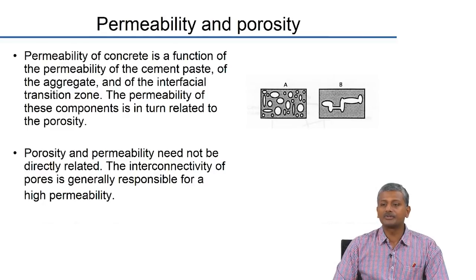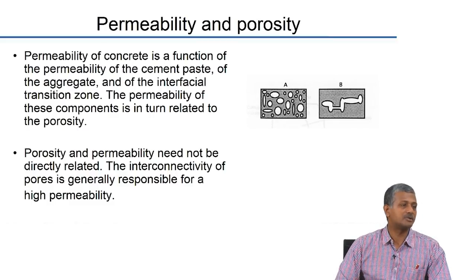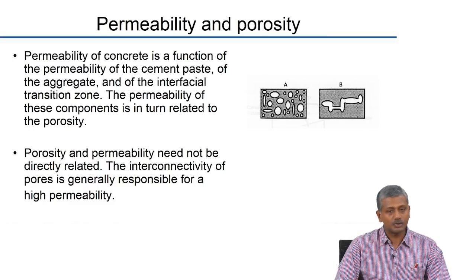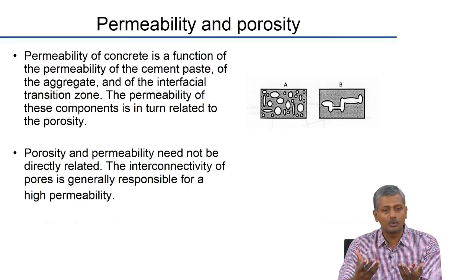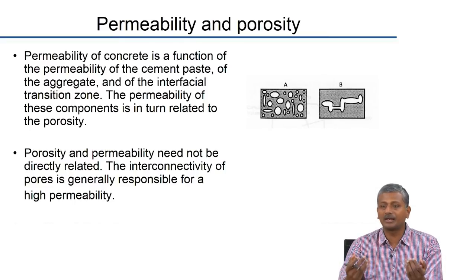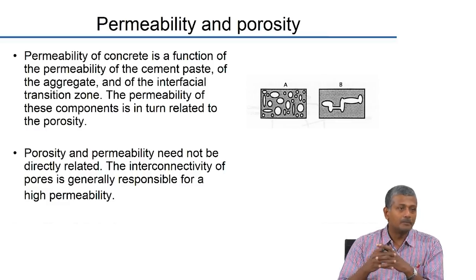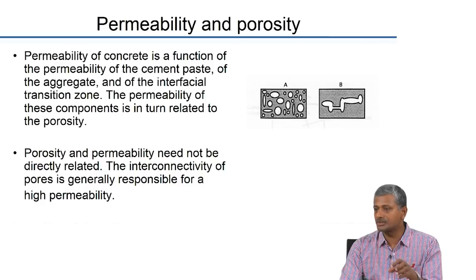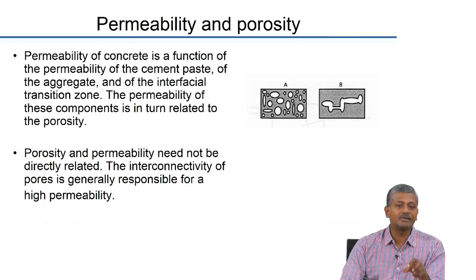Now, permeability of course is related to how interconnected the pores are, okay, and porosity is determined by what? What determines the porosity of a concrete? The water to cement ratio determines the porosity of the concrete, okay. But then the water to cement ratio also affects the permeability of the concrete. The higher the water to cement ratio, the larger the amount of pores, the greater the chance that these pores are interconnected. But it does not necessarily mean that if you have an air entrained system which has more porosity, the air entrained system will also result in greater permeability. It is not necessary.